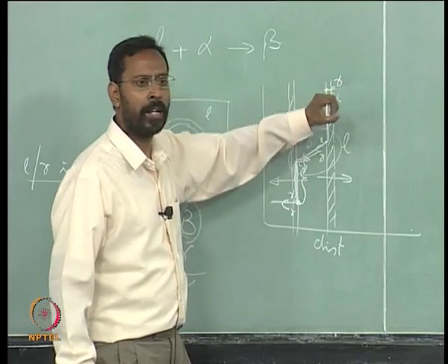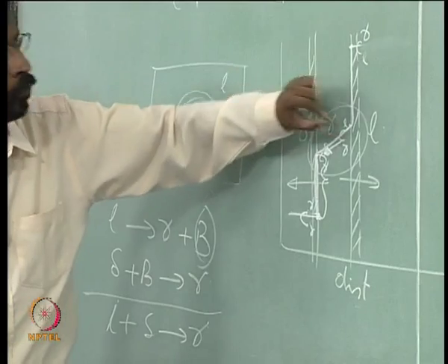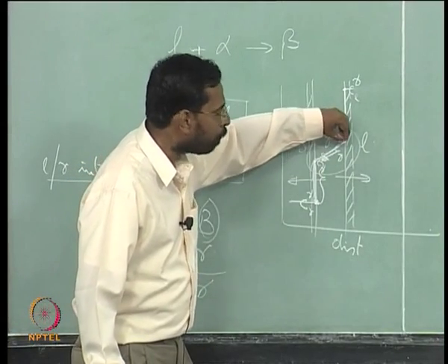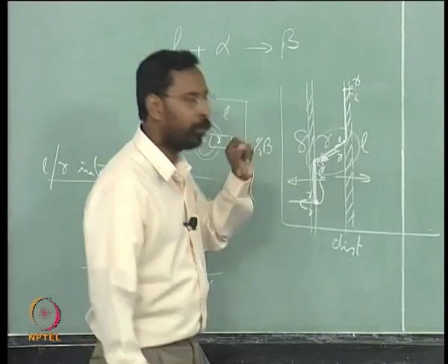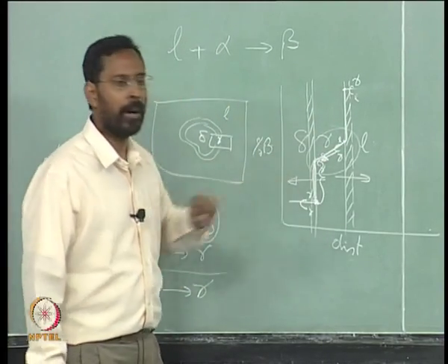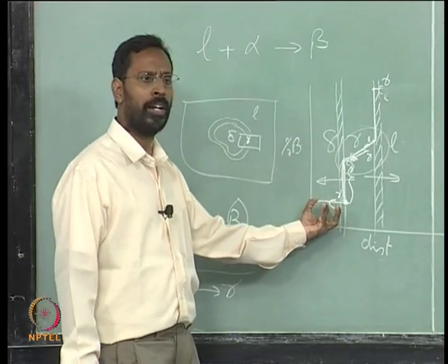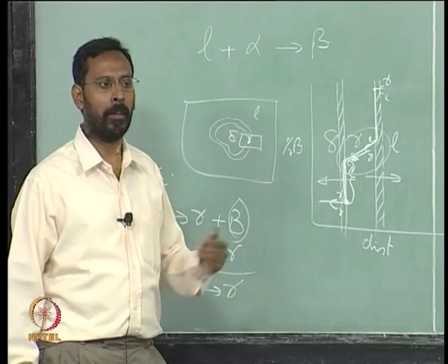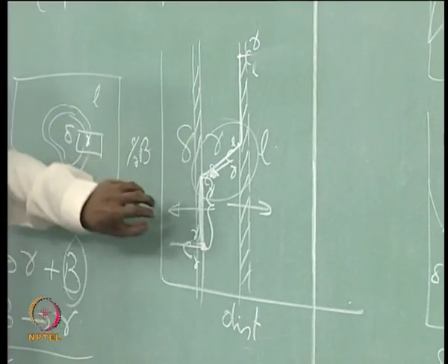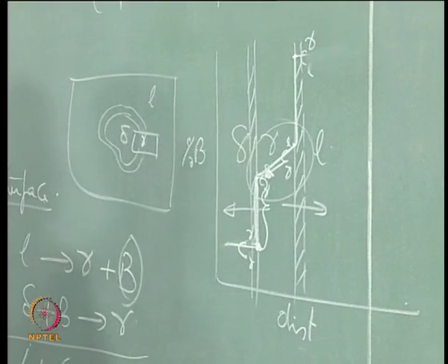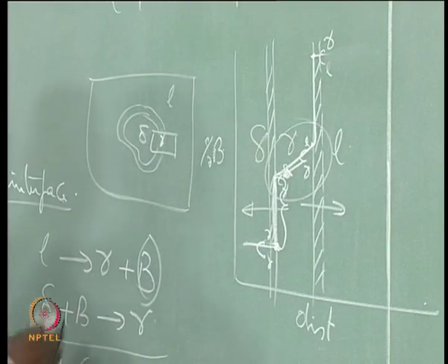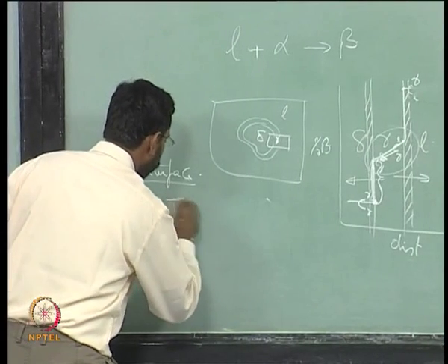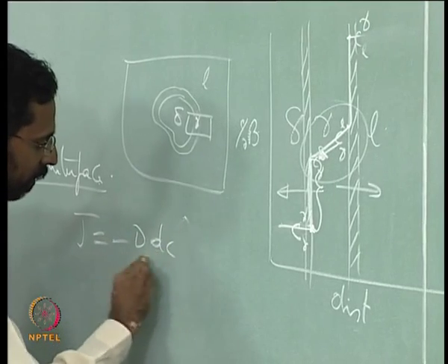So, the excess B atoms are rejected out, and a small volume of liquid gets converted to gamma, and in the process the B atoms that are rejected out travel through the gamma and then reach the gamma delta interface and get added to the delta which is available, and the carbon content, or the B content, of the delta rises in such a way that some part of the delta gets transformed, and all this is driven because of diffusion. And again we all know J is minus D dC by dx.